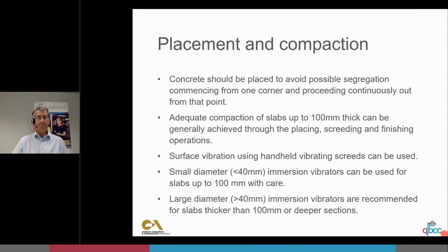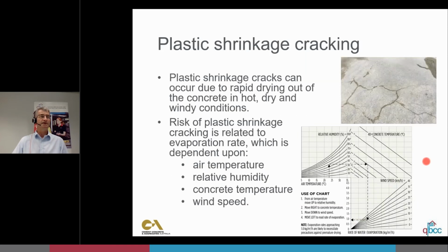Okay, plastic shrinkage cracking. This is pretty common. You can see by the picture that this cracking pattern is fairly random. So what is plastic surface cracking? Just picture a dry lake bed. You've probably all seen photos of a dry lake bed which is just all cracked. That happens when the top of that lake bed dries out and shrinks while it's still muddy underneath. That's the same mechanism for plastic shrinkage cracking in concrete.